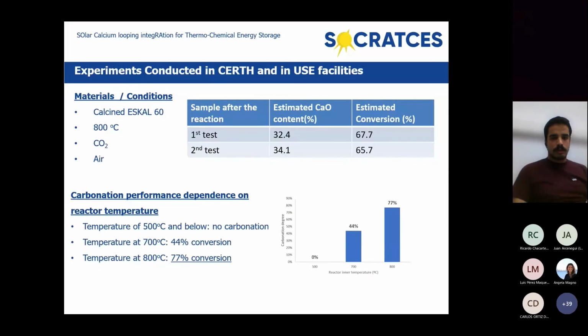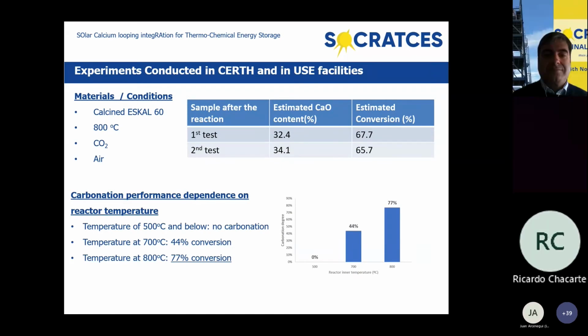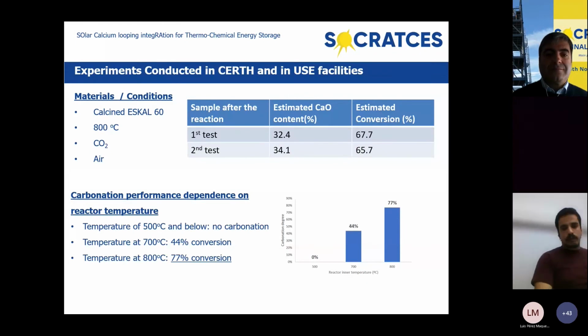And as you can see, the calcium oxide conversion depends on the reactor's temperature, where for 800 degrees Celsius, the conversion achieved was 77%, while for lower temperatures, the conversion rate drops significantly. That's all from me, and thank you for your attention.